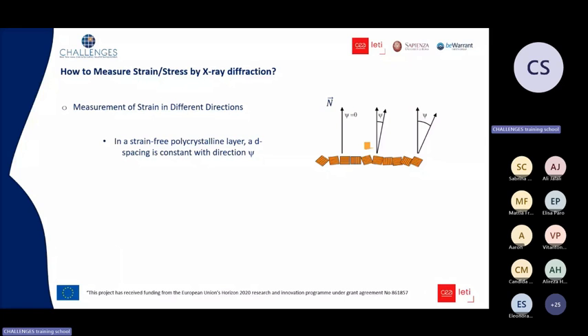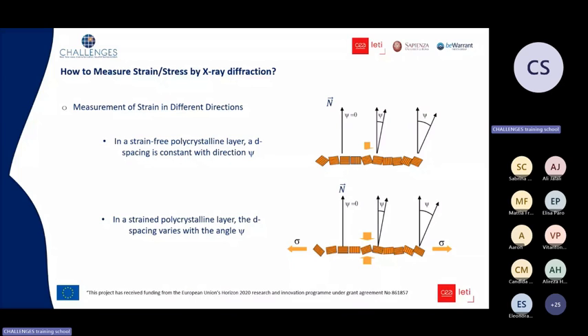So what does it mean? It means that for a strain-free polycrystalline layer, if you look at the d-spacing as a function of the tilt angle, considering that the n direction is normal to the sample surface, the d-spacing in the different grains in the material will be constant whatever the direction psi of observation. If now you apply a stress on this polycrystalline layer, the d-spacing will vary with the psi angle. For instance, in that case, for a tensile in-plane stress, the d-spacing for this grain will decrease along the psi equal to zero direction. But if you increase the psi angle, the d-spacing will increase. So this is very interesting.